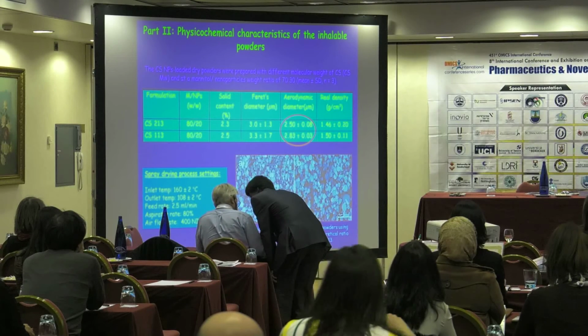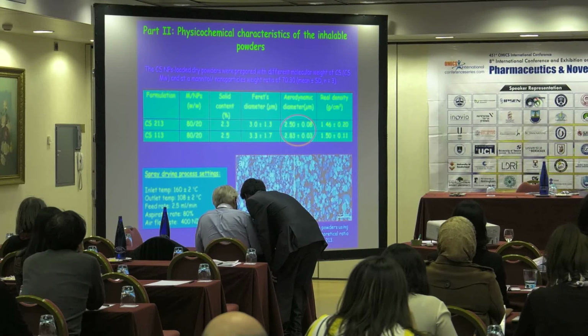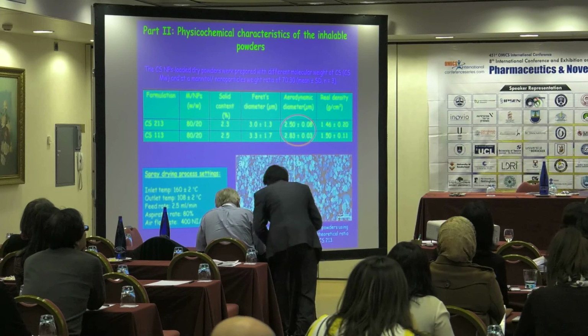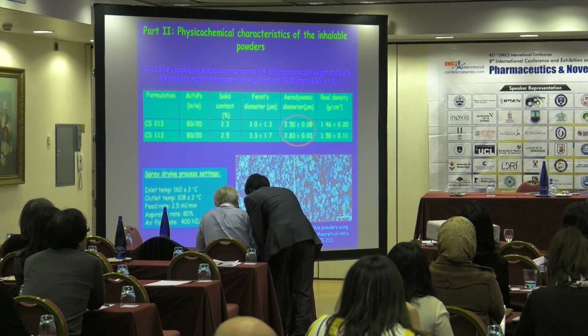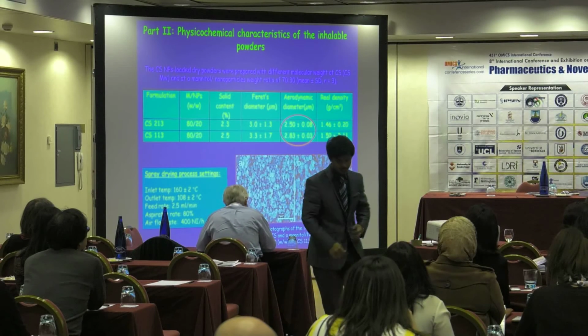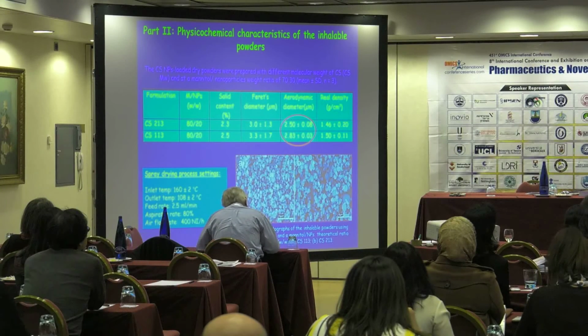We characterized the powders for their diameter, Ferret diameter, aerodynamic diameter, and real density. Most importantly, the aerodynamic diameter was between 2.5 and 2.83, which is very important. If we need to deposit inhalable powders into the deep lung, the aerodynamic diameter should be between 1 to 5 microns, and their aerodynamic diameters were in the desired range.